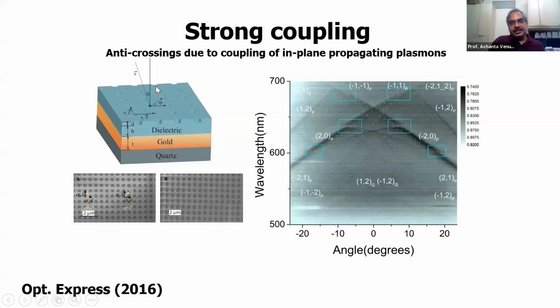Okay, so that's all in the weak coupling regime. In the strong coupling regime, one example I can give is the Rabi splitting, or so-called anti-crossings. If the coupling g is comparable to the lifetime of the photon cavity mode or the lifetime of the two-level system or the excited system, then you start seeing these strong coupling features, and one of them is Rabi splitting or anti-crossings. This is a dispersion plot, omega versus k. The angle is related to k0 sine theta, which is the momentum, where k0 is 2 pi over lambda 0, the incident wavelength.